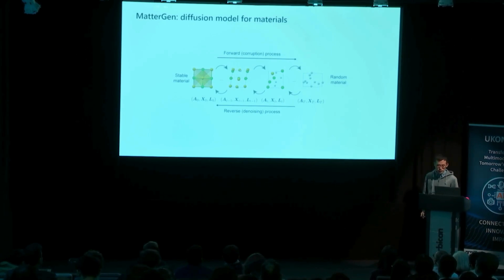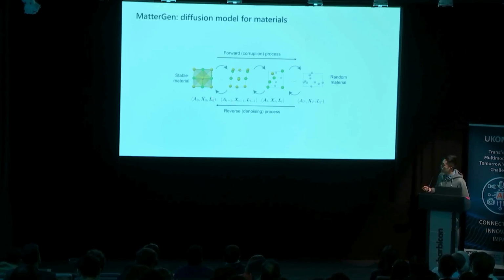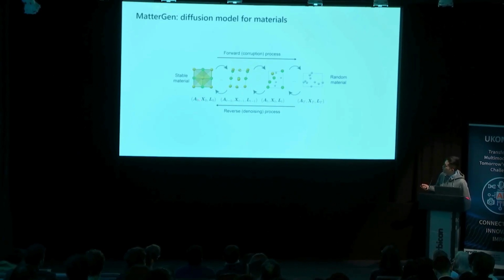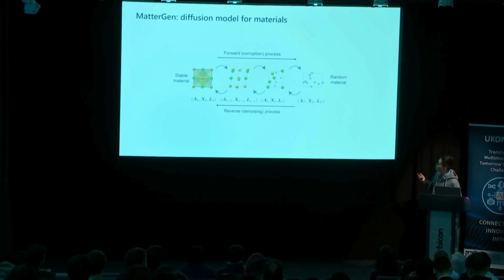The core of MatterGen is a diffusion model that is specifically designed for materials. As I described earlier, you can describe a material as a bunch of atoms, their positions, as well as periodic lattices. So we build a specific diffusion process for this type of material. During training, you take stable materials and corrupt them, both the atom types, positions, and the lattices. This gives you a random distribution from which you can sample. In this process, you learn a denoising model that can denoise a noisy material into a stable material. Therefore, during generation, you just sample a random material, and then you generate the novel material on top of it.